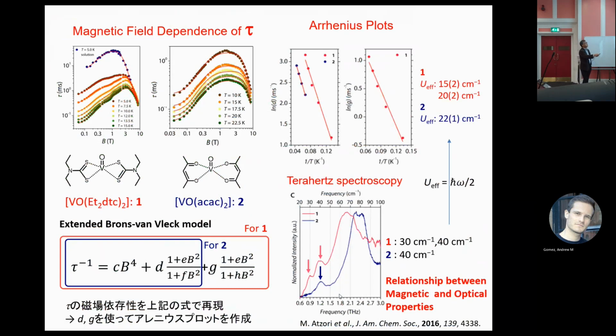You can see the terahertz. The compound with 2 relaxation times has 2 peaks in the terahertz. This is a molecular deformation, molecular stretching, and the compound with 1 relaxation time shows only 1 stretch mode in the terahertz. So we realize the relationship between magnetic and optical properties. So magnetic and optical properties are strongly correlated.